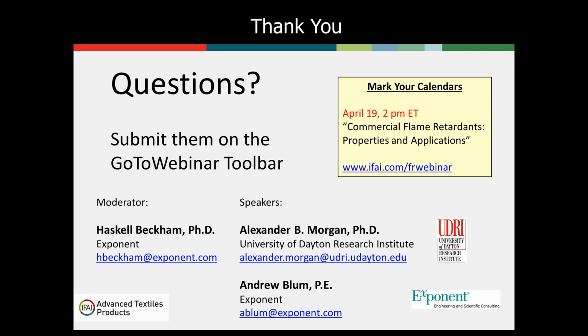Gotcha. Does the shape or size of the sample affect the heat release rate? In the MCC, no. In the cone calorimeter, yes. The size of the sample, according to the standard, is supposed to be a 4-inch square. So assuming you're testing everything as 4-inch squares, you should see the same thing. But sample thickness and the areal density of the fabric will change the result.